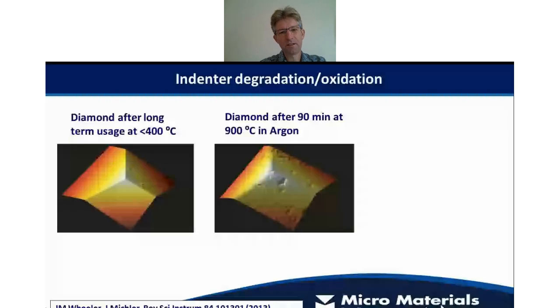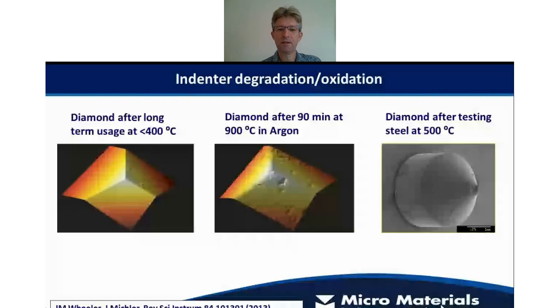This is another image. In this case, this indenter hasn't even been used for high temperature tests, but it has been exposed to argon atmosphere at 900 degrees for about an hour and a half. And you can see already you're getting some pitting in that material, and its area function effectively is going to change when you use high temperature tests, and it's going to make the test data a lot more problematic.